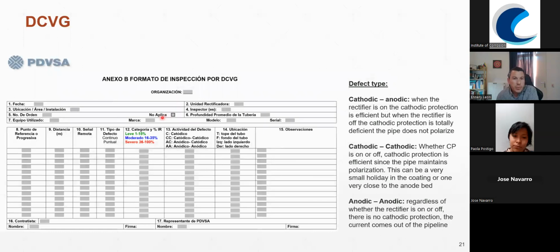Okay, I also mentioned that with DCVG, we can have an idea of the defect type. So we can say if we have a cathodic-anodic defect, and this is when the rectifier is on, the cathodic protection is efficient, so it is protected. But when the rectifier is off, the cathodic protection is totally deficient, so the pipeline doesn't polarize, it's going to corrode. Then we have a cathodic-cathodic defect, that if the CP is on, the pipeline or that defect is protected.